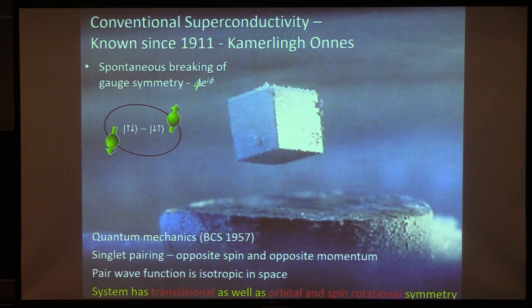And what characterizes the overall macroscopic state of this condensate is this order parameter, and you see it has an amplitude delta, but it also has a phase, and this phase is spontaneously chosen. So if you just take a chunk of superconductor, you can easily measure what delta is, but phi will be arbitrary.